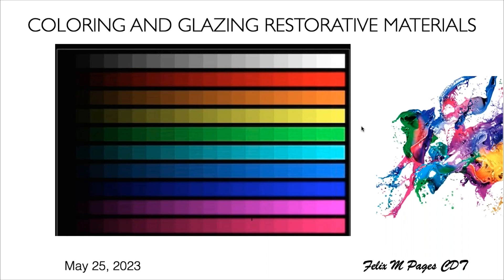When designing a framework or substructure to layer, if you have too much material in the interproximals and don't give the ceramist room for micro or macro layering, you'll have problems. If you have a really thin porcelain overlay, it doesn't have enough thickness to carry color. You're mostly dependent on the color of the zirconia, lithium disilicate, or PFM base. For PFMs, the opaque needs to be modified to already look like the final shade, because light doesn't go through metal.